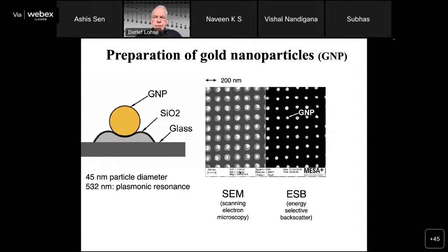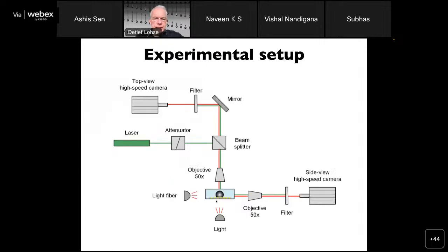Well, how do we prepare the gold nanoparticles? This is done in the clean room. The nanoparticles are typically 45 nanometers in diameter, and we place them on some substrate. Here you see pictures by SEM, scanning electron microscopy, and by energy selective backscatter. And that we then place in the liquid here. So it's sitting right here. And we look from the top with a high-speed camera, and we also look from the side with a high-speed camera. And we couple in the laser towards the particles so that we can heat those particles and create these bubbles.